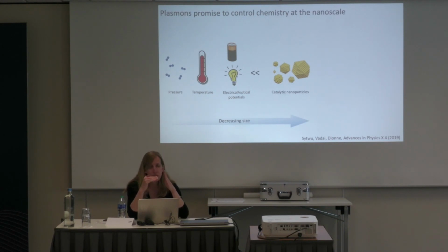It also determines, as you'll see in some of the hydrogen splitting, how the hydrogen intercalates into the surface and the subsurface of some of these catalytic nanoparticles. And what we'll see is that, especially in these hydrogenation-based reactions, you want to have splitting of hydrogen, but you also want to have a little bit of a reservoir of hydrogen in your nanoparticle. And that surface faceting will determine how deep and how far the hydrogen goes into the nanoparticle.